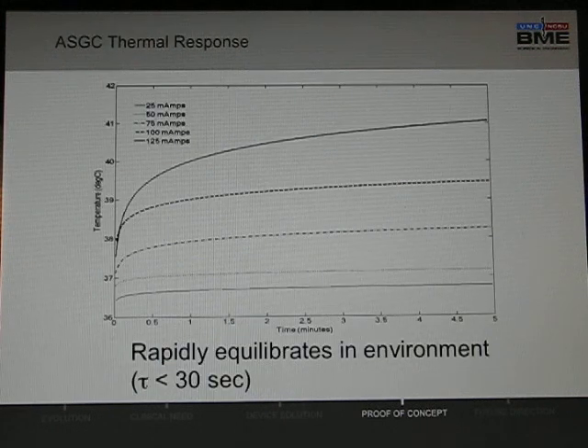Here we've plotted the thermal response of the catheter, temperature versus time. As you can see, the catheter rapidly equilibrates with its environment, and has a time constant of less than 30 seconds for all currents applied.